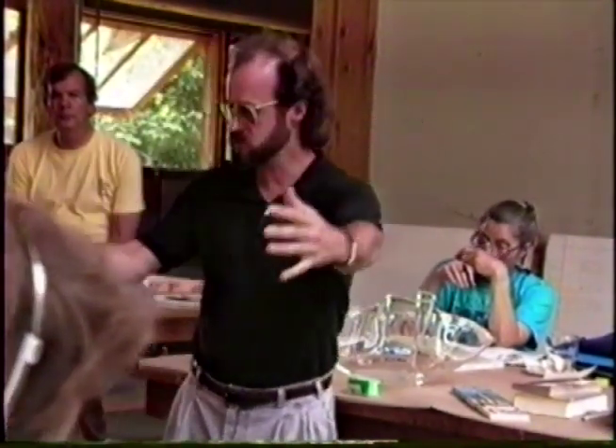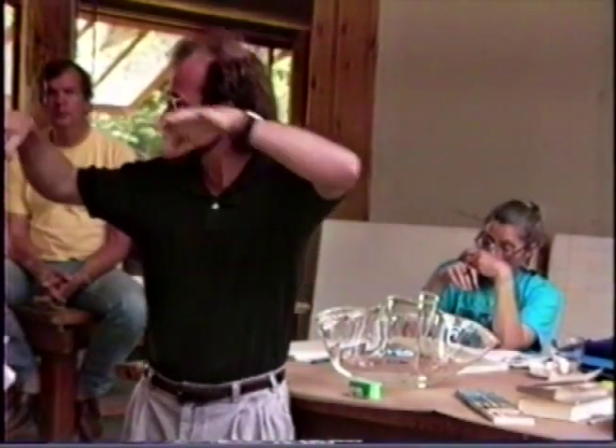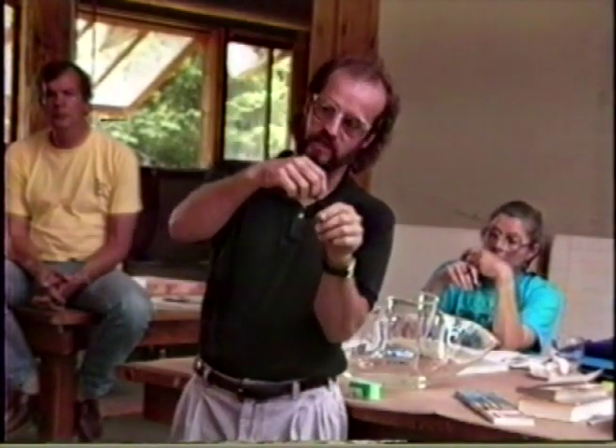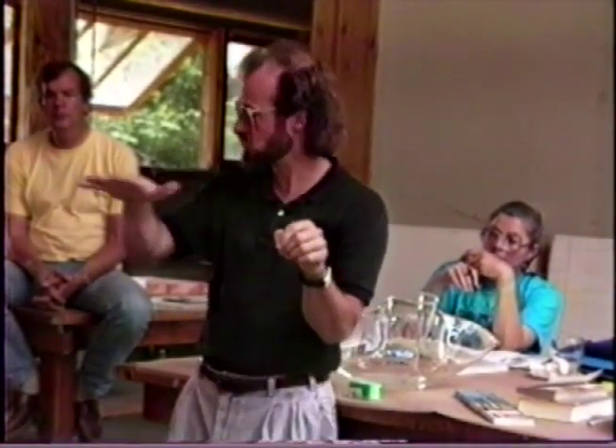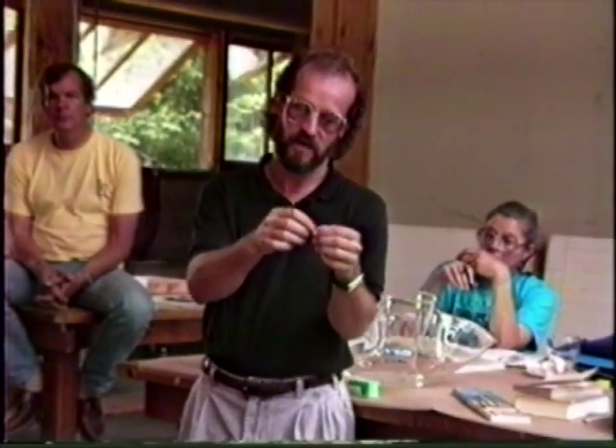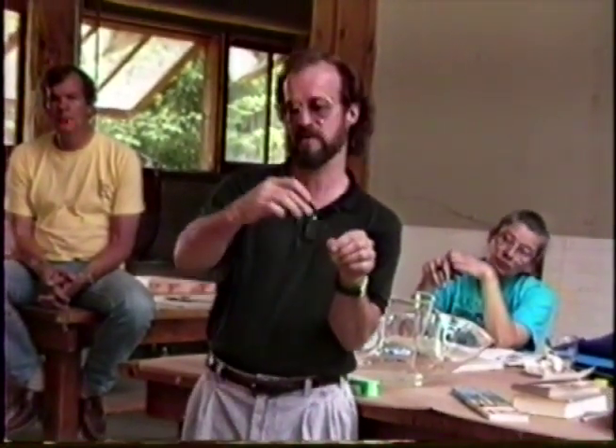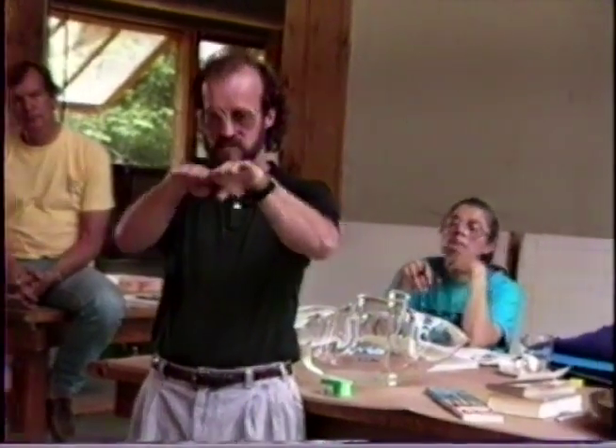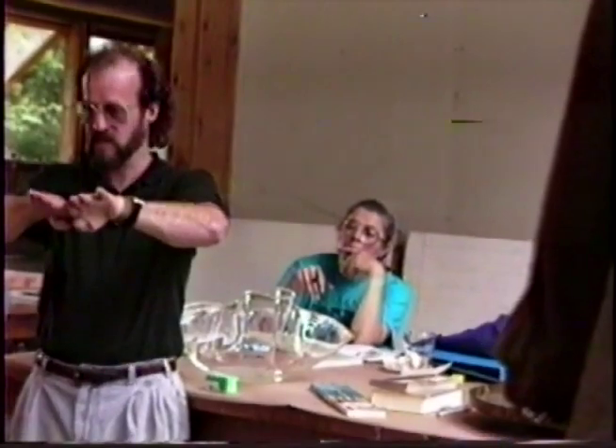So there are ways to deal with that. One, I work with one solid piece of clear and second layers and maybe third layers on top of that. Now if you take that on a kiln shelf and put little chips of glass around the edge, so if I've got clear and I'm going to full fuse, I'll put little 1/8 inch by 1/8 inch chips about every 6 inches all the way around my piece. It holds that glass up off the shelf about 1/8 of an inch, so that when it slumps, the center will go down first and push the air off the shelf so you don't get any air trapped under there, and that way you can fuse large pieces without blowing holes in it.